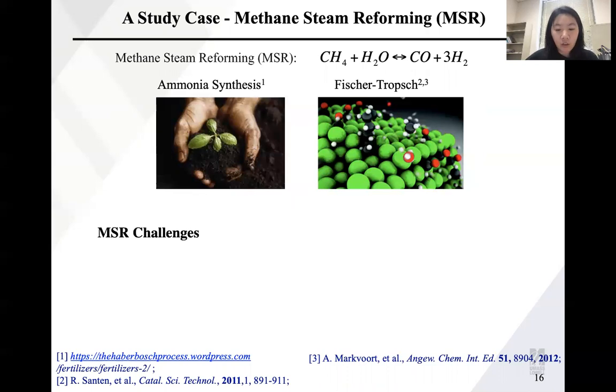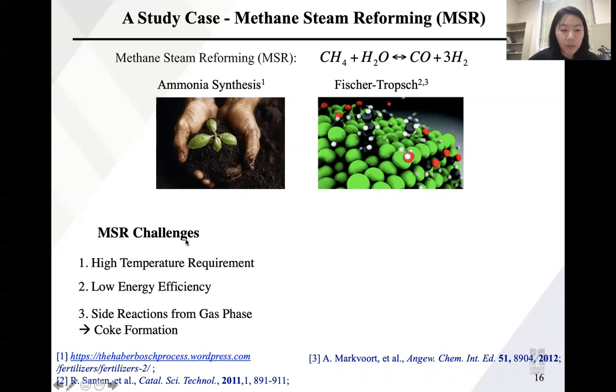And there are also challenges of methane steam reforming reactions with conventional heating. Because of the high temperature requirement, the methane steam reforming reaction always has low energy efficiency in industrial applications. And also because of this high temperature requirement, with conventional heating everything is heated uniformly, so you will have a very high temperature of the gas phase that will lead to the side reaction, which is coke formation. And after coke forms, it will deactivate your catalyst. Then the stability of this reaction is also not good in industrial applications.